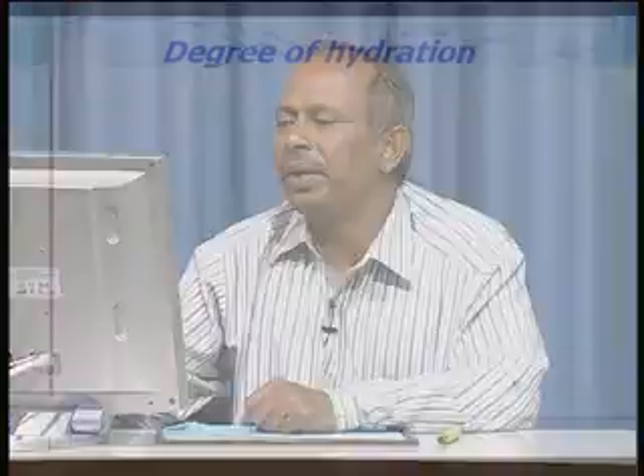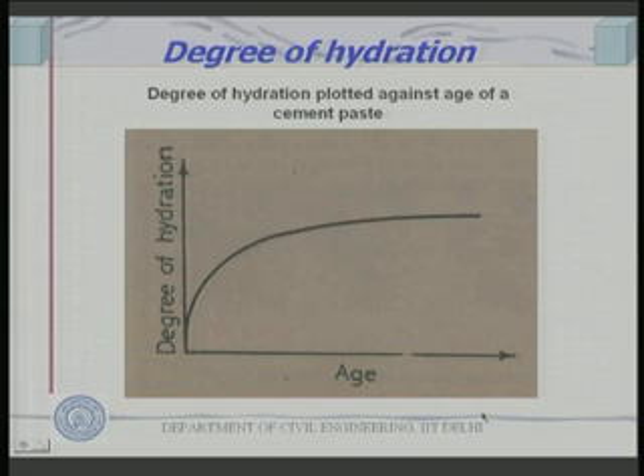So, degree of hydration changes with age, as we have defined. As the age increases, degree of hydration increases, the fraction of cement that is reacting increases. But if the water cement ratio is less than 0.36, you can't get complete degree of hydration. In fact, the alpha max will be given by W by C divided by 0.36. For example, if the water cement ratio is 0.3, maximum degree of hydration attainable is 0.3 divided by 0.36.